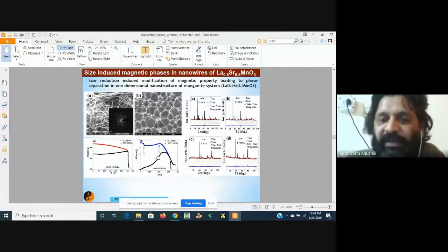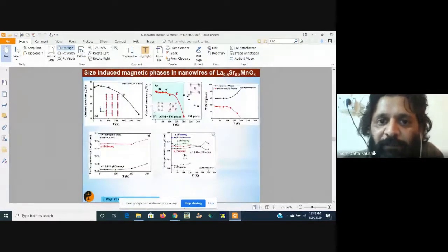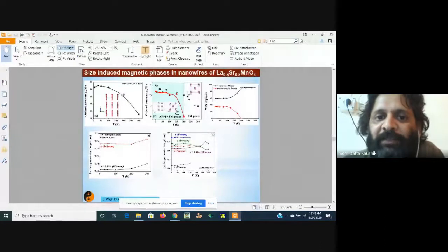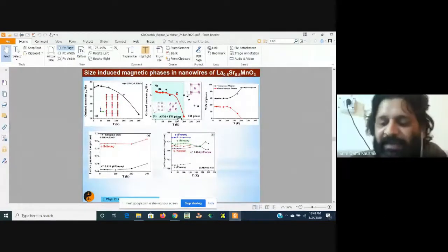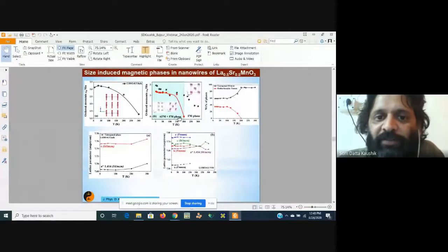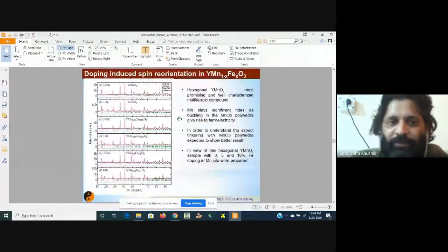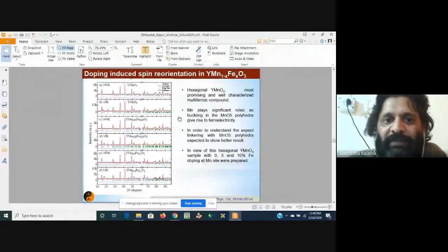But upon carrying out the neutron diffraction, we could identify that there was a phase coexistence below 200 Kelvin. So below 200 Kelvin there were two phases: one is an antiferromagnetic phase, another is a ferromagnetic phase. So the idea is that by using neutron diffraction, there are n number of things in magnetism itself you can try to understand. I'll show you one or two more examples. After that, we can conclude.